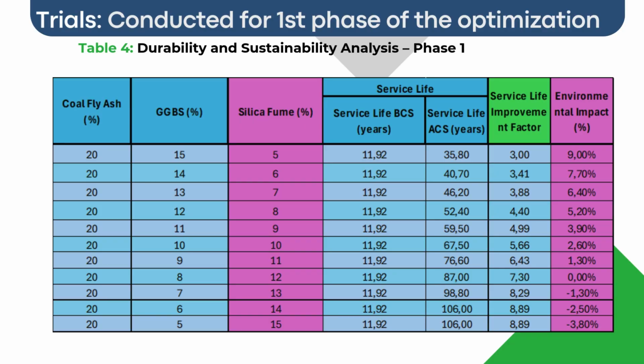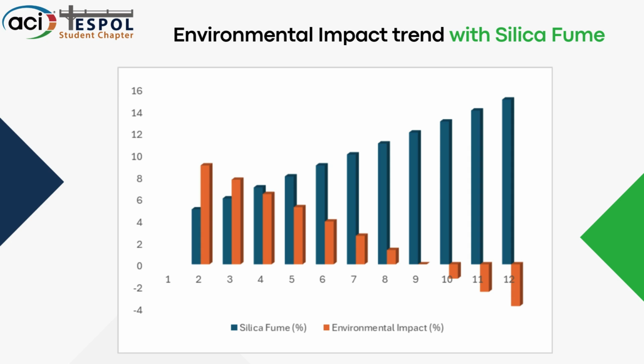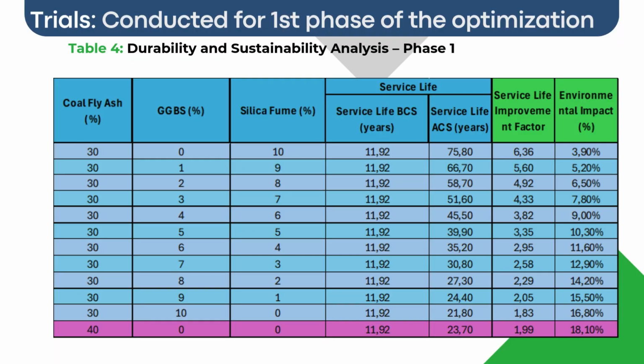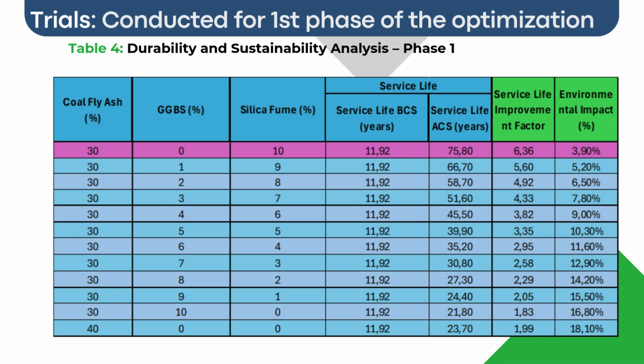In the second dosage, we used 30 and 40% fly ash with GGBS and silica fume from 10 to 0%, seeking a balance between durability and environmental impact. The best environmental performance was achieved by replacing 40% of the cement only with fly ash, due to its low carbon dioxide emission. The longest useful life, but with less reduction in environmental impact, was achieved with 30% fly ash, 0% slag, and 10% silica fume, showing the high impact of silica fume. On the other hand, with 30% fly ash and 10% GGBS, the shortest useful life was achieved, but with a greater reduction in environmental impact, reinforcing the negative effect of GGBS in ecological terms.